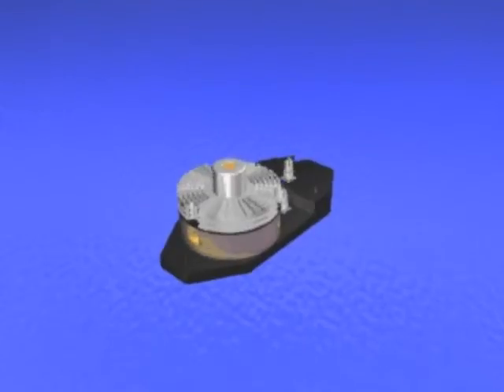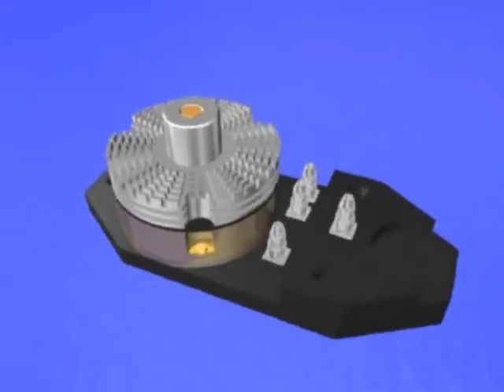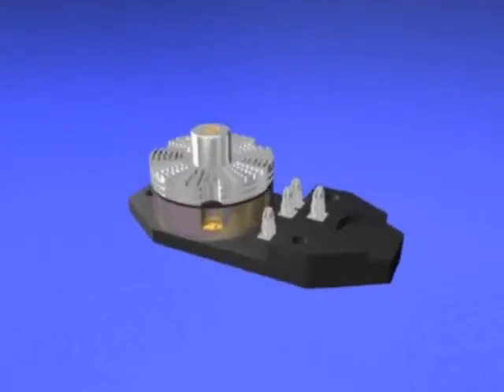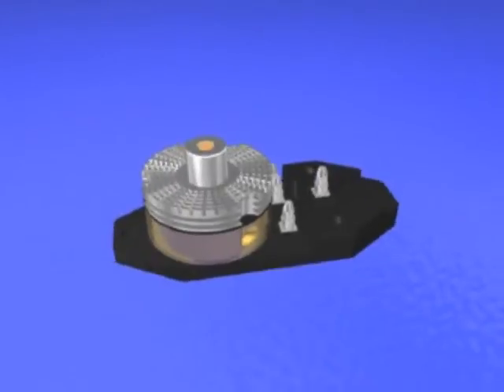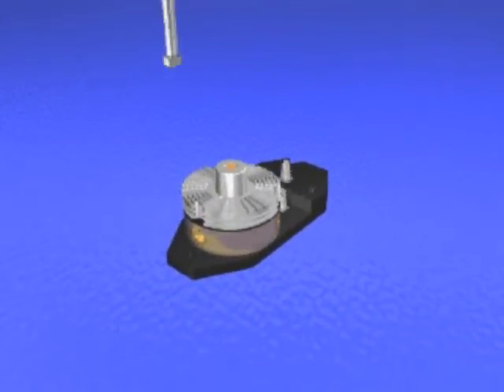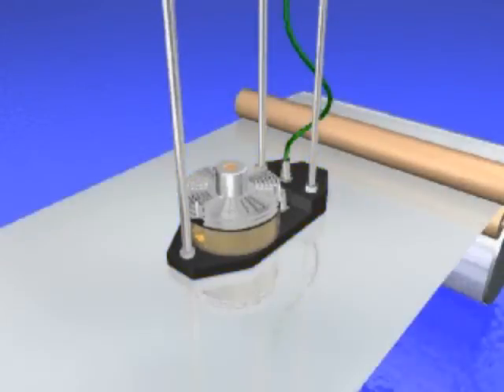IMPOC is an innovative quality assurance system for the non-destructive material testing of steel strip during strip processing, which gives complete evidence of the quality of the entire coil. The IMPOC measuring system is a magnetic inductive testing instrument for automatically ascertaining the tensile strength and yield point of ferromagnetic steel strips.